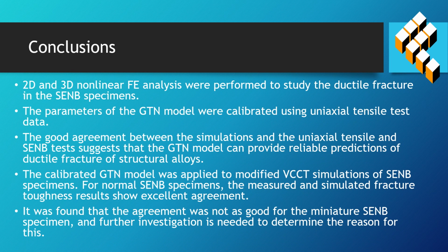Conclusions: 2D and 3D nonlinear finite element analyses were performed to study the ductile fracture in the SENB specimens. The parameters of the GTN model were calibrated using uniaxial tensile test data. The good agreement between the simulations and the uniaxial tensile and SENB tests suggests that the GTN model can provide reliable predictions of ductile fracture of structural alloys.